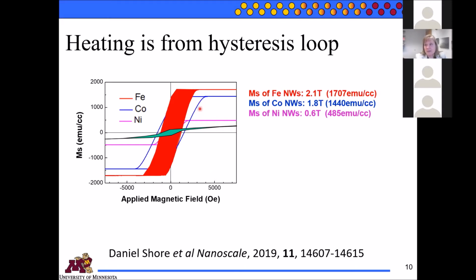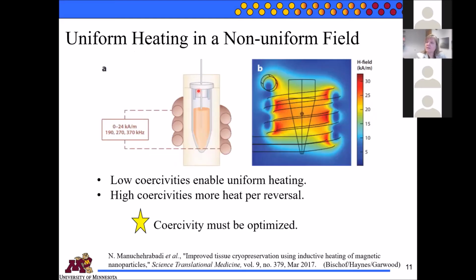Our single wires, now we start to see switching because there's interactions between our wires based on the way they're made. But when we separate the wires and measure individually, then we have a sharper switching field. And I will show you here why that matters. This is again from that paper by my colleagues. They did a micromagnetic simulation of the field strength throughout their coil that they're using for nanowarming.